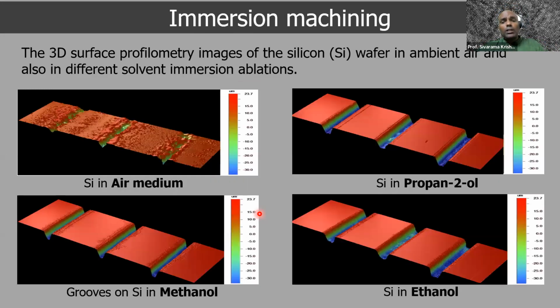But then one of the first pieces of research, which was fairly successful, and Mano came up with this looking into literature, is to enhance the smoothness of these grooves, which is to say that reduce the roughness in as few a number of passes as possible in ablating material. So he took the most common material that one would want to do, one of the most common, which is silicon wafers, and under identical conditions, he ablated the silicon wafer in air, that's ambient conditions. He immersed the silicon wafer in propanol, in isopropanol, a very common solvent, then in methanol and in ethanol, and